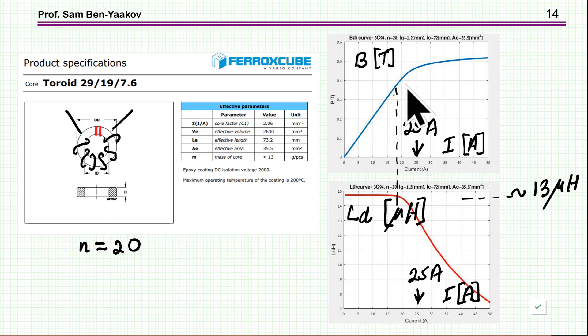Again, you see that indeed in the area where the inductance is still about constant, it is even linear even at higher current. Because when the relative permeability drops a little bit, then still it works pretty good. But as the permeability really drops a lot, then we are losing the gain. So the point is that over the range of current that you'll be using this inductor, you'll get a pretty good measure of the current by measuring B in the gap.